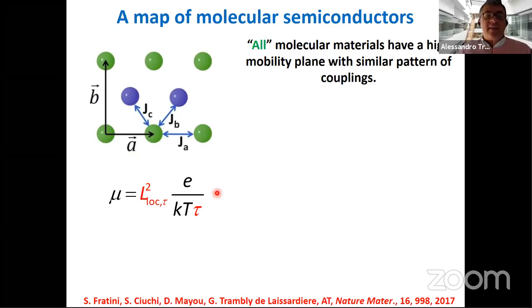But the idea is that now, with an expression like this, we can study 1,000, as many systems as we like. And what we decided to do was to build a map of all possible semiconductors. We looked around at what is out there and noticed that in all semiconductors, we have a molecule coupled to essentially 3 neighbors, sometimes 2, but this does not change the generality of the model. And we compute the mobility for all possible couplings between molecules, using the experimental range as a guide to what was relevant and what was not.